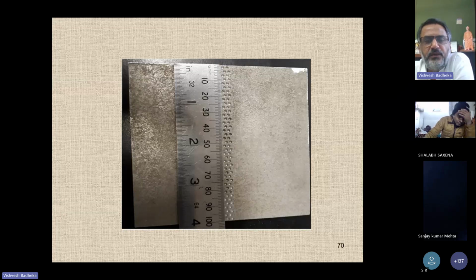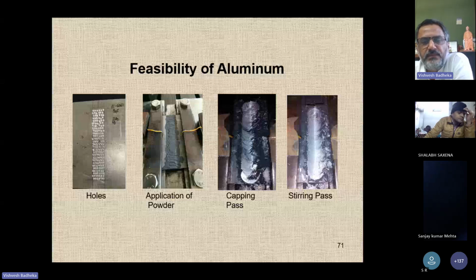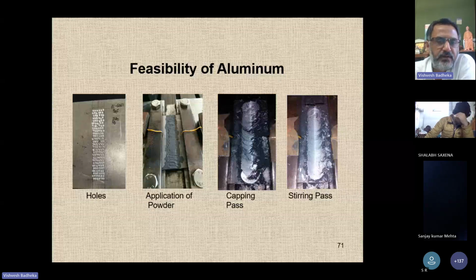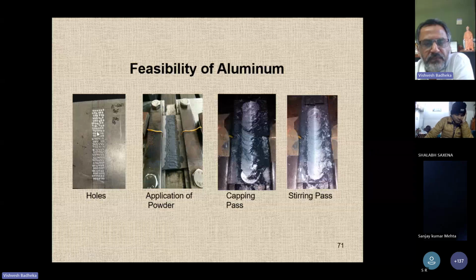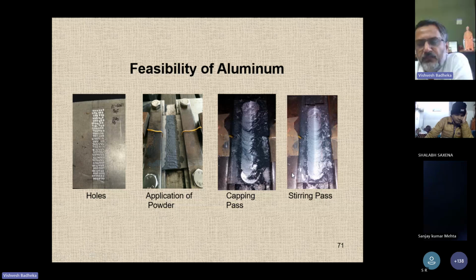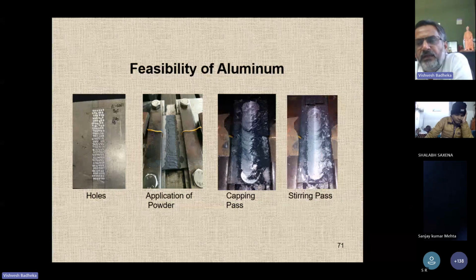Moving further, you can see there is an initial feasibility study which was done in our laboratory, wherein you can see the hole pattern created with the help of a very simple drilling machine. Then you fill the holes with the reinforcement. The reinforcement is mixed with acetone and applied with a paintbrush. Then you can see the capping pass has been done, and the stirring pass has been done, so that the reinforcement has mixed with the aluminum metal matrix. So this is how it can be done.